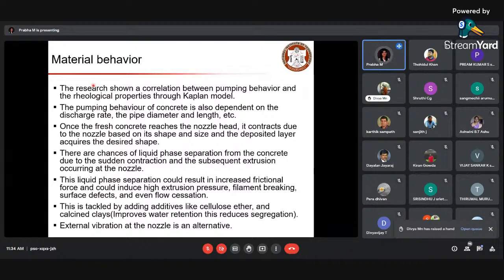There are chances of liquid phase separation. That's what I was talking about regarding rheology. The mix should be as homogeneous as possible so that the liquid phase does not get separated from the concrete due to sudden contraction and subsequent extrusion at the nozzle. This liquid phase separation would result in increased frictional force and induce high extrusion pressure, which affects the filament. You may see a lot of surface defects, and that affects the flow cessation.